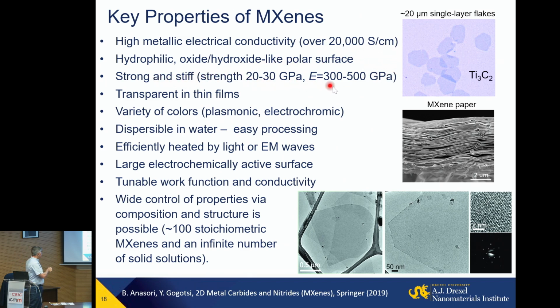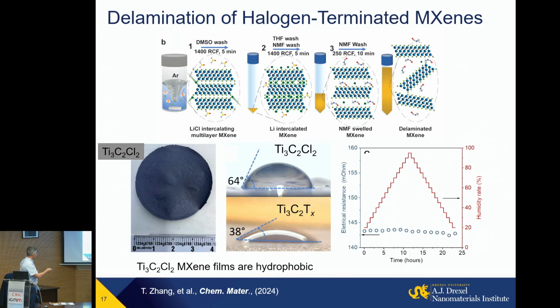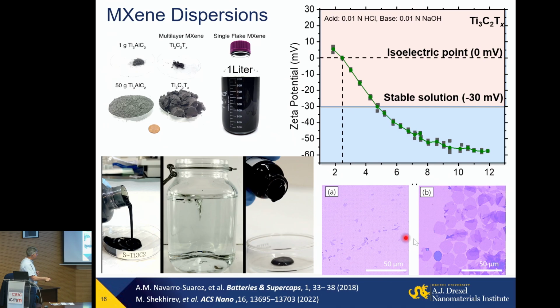They're very strong. Actually, they are stronger than reduced graphene oxide or graphene oxide, compared to materials that are used in practical application, not an ideal sheet of graphene. And these flakes are about 20 microns. You see more of these flakes here. Those are flakes on a silicon wafer. The lighter ones are single layer flakes. I've never seen oxide, hydroxide, dichalcogenide flakes produced from solution in that size. And dispersion is very easy.